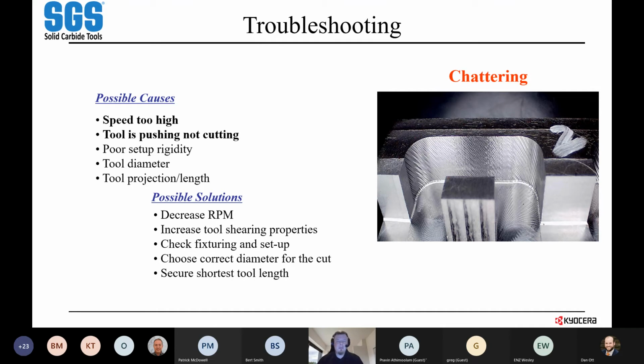because sometimes you have to use a smaller diameter tool with a long length of cut. So having variable geometry, uneven flute counts, things like that, really help to lower that. And then I've already touched on projection and length. So you can always play with lowering your spindle speed, allowing the tool to bite more effectively and get a better cut into the material, looking at a tool with better shearing properties. Higher rake angle, higher helix, it's just going to cut more efficiently and dig into the part in a good way. And then of course check your fixturing and setup, make sure everything's really rigid,